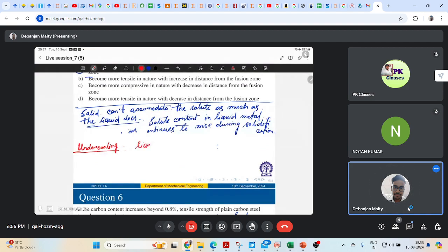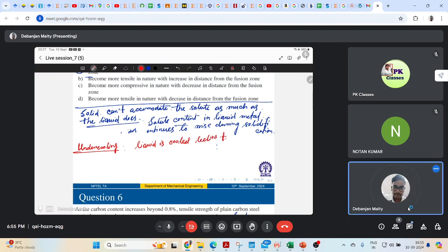So liquid is cooled below its normal freezing point without any phase change. What factors can influence undercooling? The first and foremost thing is cooling rate. If you're cooling it very fast, faster cooling will lead to a high degree of undercooling because there will be less time for nucleation to occur, right? So cooling rate is one parameter.